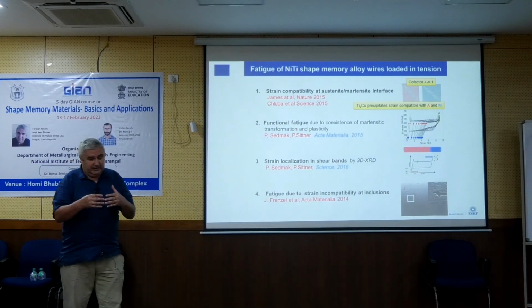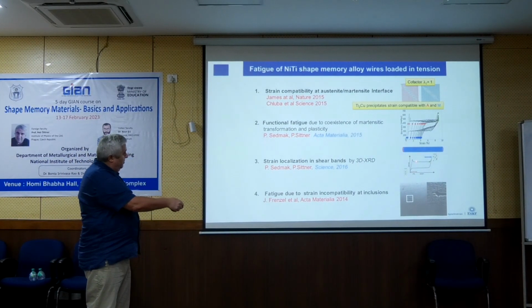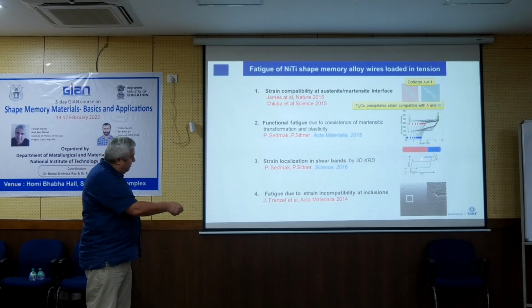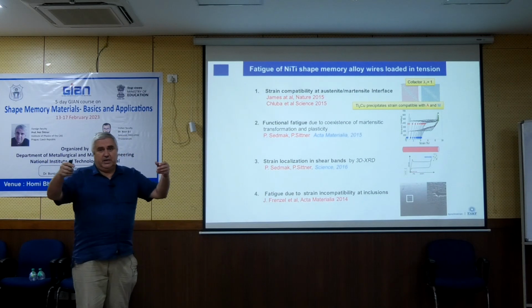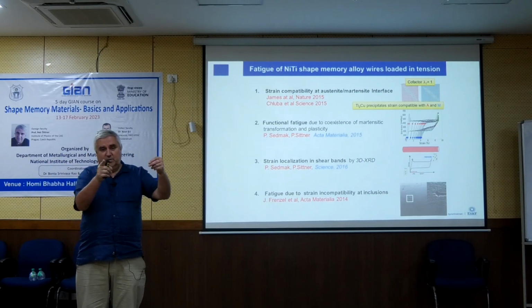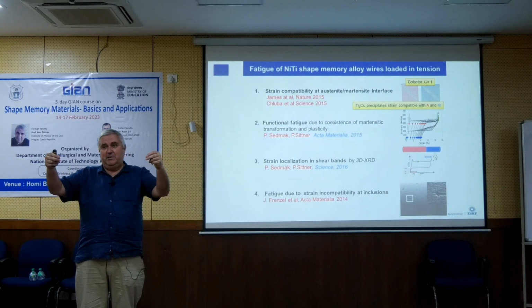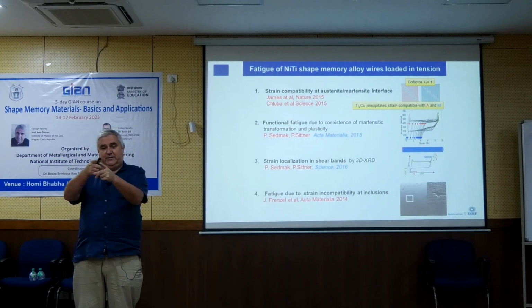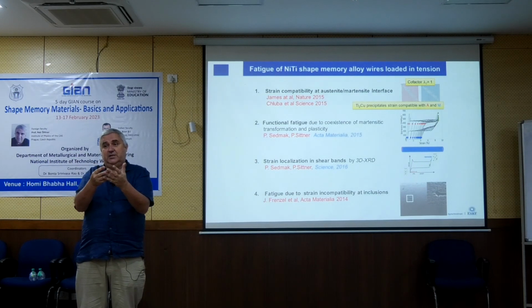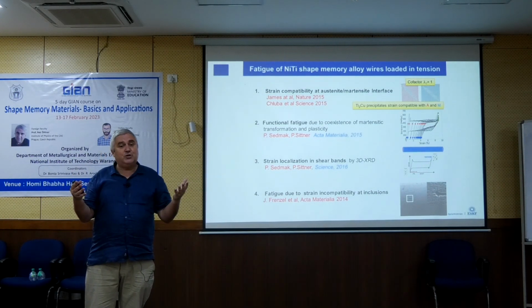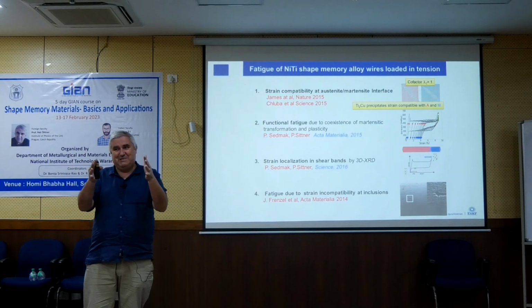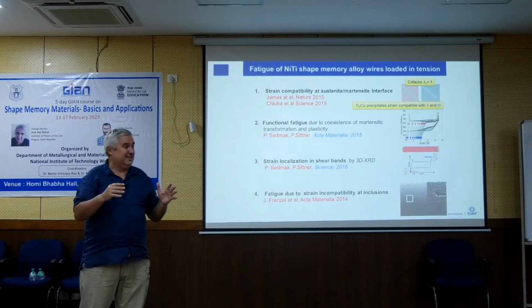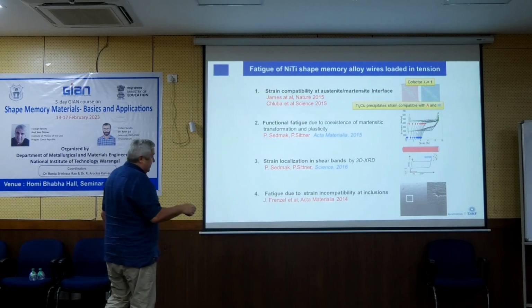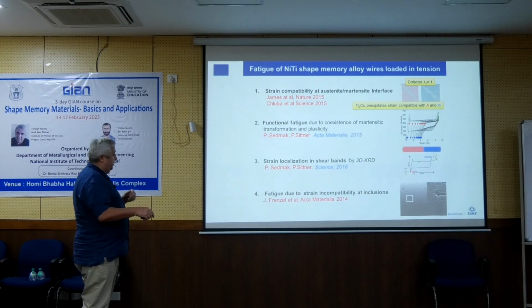Imagine that you have this, but now you stop. And now you stop here in the middle, and you start to cycle. So what will happen? You will cycle, and the band will move like this. So you apply an amplitude like 1%, but you will have 10% here. And of course, this localization is a killer for any fatigue. Fortunately, if you do that, the localization will spread and the sample will somehow deal with that. But it is definitely a problem which has to be considered in functional fatigue.